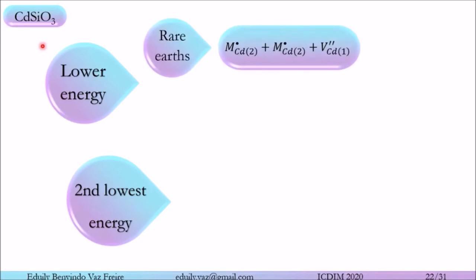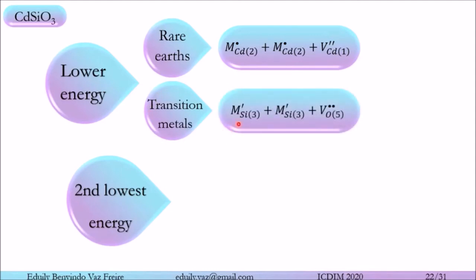Okay, now we will see the bound defects, and for that we chose the first and the second lowest energy forms for the extrinsic defects, okay? These calculations were only done for the CdSiO3 matrix, okay? The lowest energy defect we have for rare earths is with two doping ions at the cadmium 2 sites plus a cadmium 1 vacancy. As for transition metals, the least energetic defect is with the doping ions at the silicon 3 sites plus an oxygen vacancy 5.